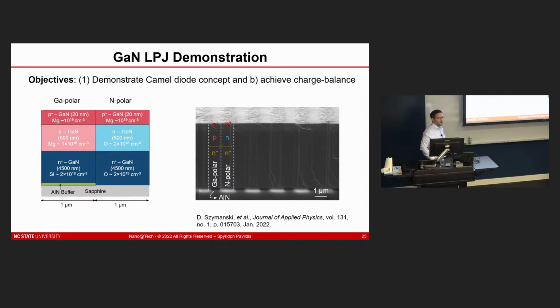But during high temperature annealing, what happened between the P and N? Is there some lateral diffusion? Okay, sorry, yeah. For this sample, we do not do this ultra-high pressure annealing. These are two completely separate approaches. The ultra-high pressure annealing that I showed at the end of the presentation is something that we're leveraging in combination with magnesium implantation. That is to repair the crystal and activate the implanted magnesium.